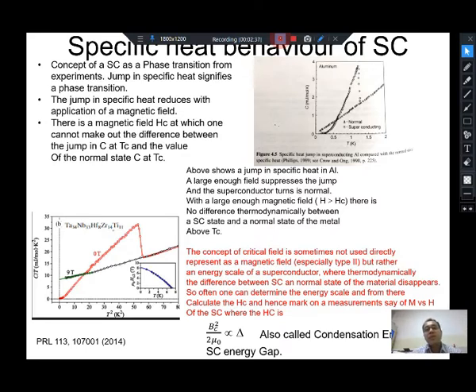And the first experiment that I show you is a measurement of specific heat in aluminium. Specific heat as a function of temperature in aluminium. And you can see that if you cool this aluminium superconductor, then below its transition temperature, which is located here, you see a large jump in specific heat. So if you are measuring, for example, resistance as a function of temperature, then between 1 and 1.5 Kelvin the resistance would go to 0, and wherever the resistance goes to 0 at the critical transition temperature, the specific heat shows a very sharp jump. It rises up and then falls down.